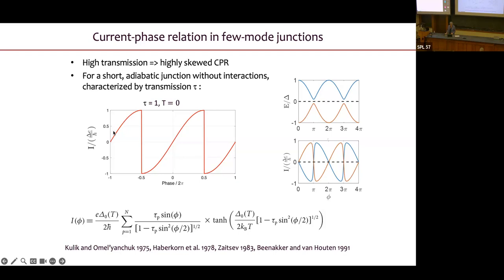Whereas I told you that for a conventional Josephson junction, the current phase relation is sinusoidal, this is clearly not at all sinusoidal, right? It's not exactly a sawtooth, it's got this very characteristic roll over here, but it's sawtooth-like, it's very skewed. It's completely different than the current phase relation that you would get with the classic sinusoidal Josephson current phase relation. So this kind of current phase relation is basically an indication that you have Josephson coupling between two superconductors through a region in which you get this kind of Andreev bound state.